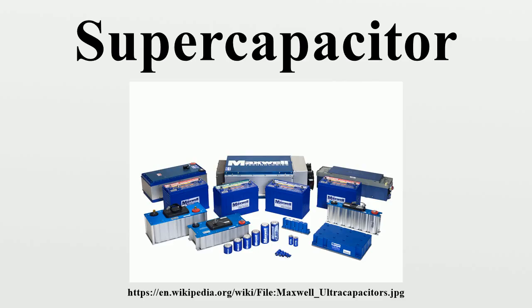The electrons reaching the positive electrode do not transfer to the anions forming the double layer. Instead, they remain in the strongly ionized and electron-hungry transition metal ions of the electrode's surface. As such, the storage capacity of Faradaic pseudocapacitance is limited by the finite quantity of reagent in the available surface. A Faradaic pseudocapacitance only occurs together with a static double-layer capacitance, and its magnitude may exceed the value of double-layer capacitance for the same surface area by a factor of 100.